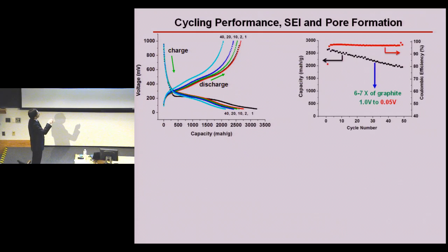One is the capacity, basically the charge you can store per weight of the electrode. You can see here we can easily get 2,500 milliamp hour per gram for this kind of core-shell structure. And the other important parameter is the Coulomb efficiency. It's basically the ratio between the number of charge you take out and the number of charge you put inside the structure. You can see here the first Coulomb efficiency is about 80%. So that means about 20% of the charge you put in is actually wasted.